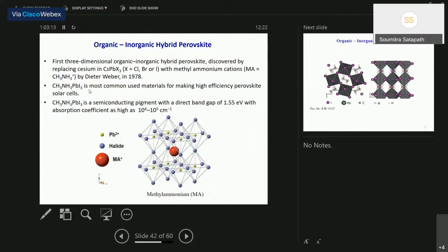And here the X is the halide: chlorine, bromine, iodine. This semiconductor, CH3NH3 lead iodide, is a popularly used organic-inorganic hybrid perovskite in perovskite solar cells, which has given an efficiency of near about 25%. It is a direct bandgap semiconductor with a bandgap of about 1.55 electron volt, very close to silicon, although a little bit far. And absorption is high, 10 to the 4 per centimeter. And this is the structure of the CH3NH3 lead iodide.